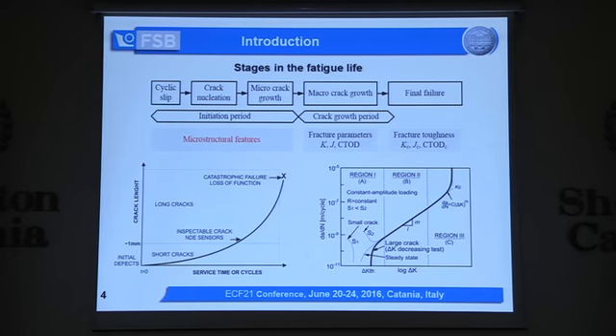Before we start, I just put here this systematization of total fatigue life, which was given by Schijve in his book. And we have the initiation period, then long crack growth, and final failure. And what we are doing here, we will consider this part, where the cracks are already long, and we'll take into account residual stresses. Without residual stresses, it's quite straightforward, but residual stresses may significantly influence fatigue crack growth rate and propagation.